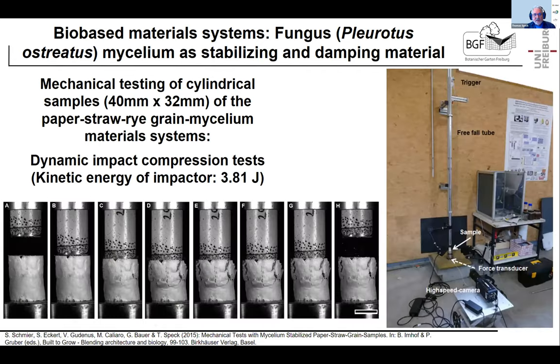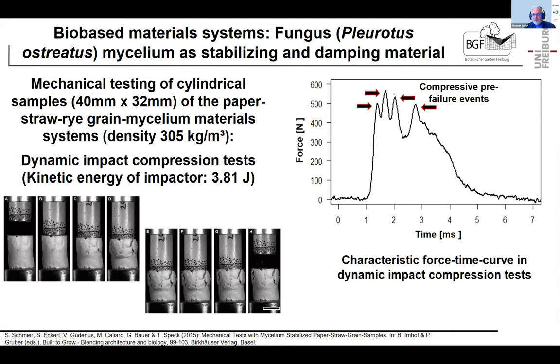What we also did, we did dynamic impact compression tests with a compression impactor with 3.8 joule. So you see the impactor falls down to the sample. We measure exactly what's going on. We have the force transduction, and how the compaction takes part. And if you look here, we find also very nice results. So we see here the force, we have compressive pre-failure events. So it shows a drastically benign failure behavior. It doesn't fail in one go.